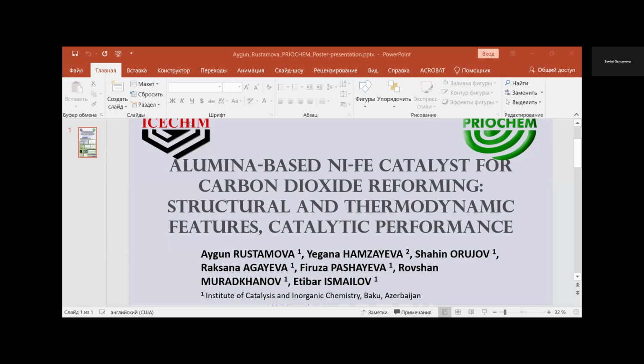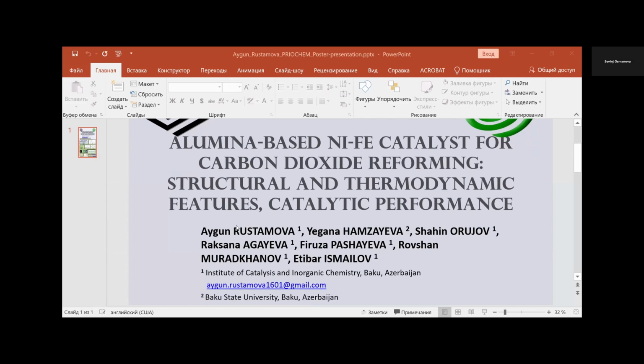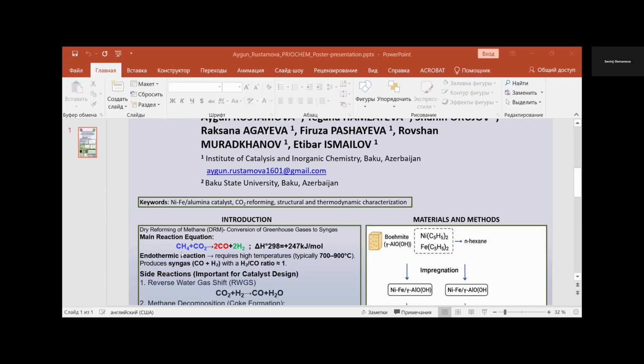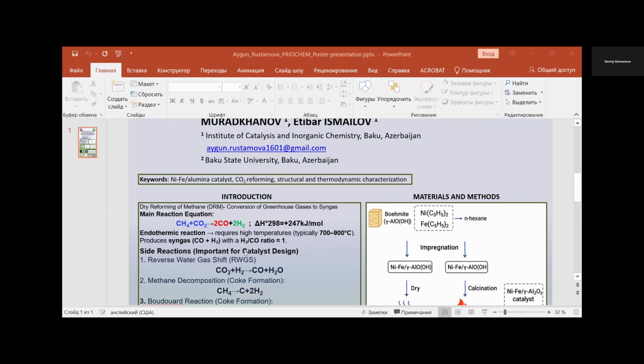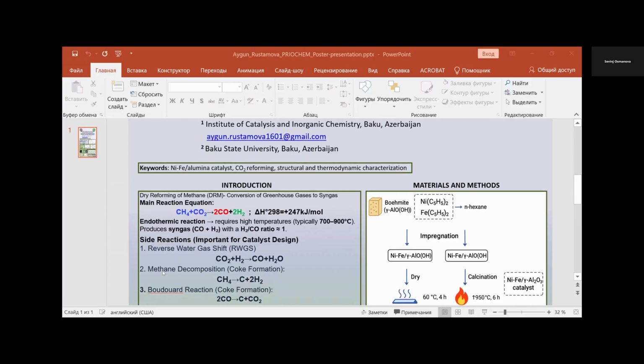My name is Shahin Orujov from the Institute of Catalysis and Inorganic Chemistry in Baku. I will present our poster on behalf of Yegane Hamzayeva. Our poster is about the aluminium-based nickel ferrum catalyst synthesis for carbon dioxide reforming. And what's actually the DRM, dry reforming of methane? The main reaction is shown here. You can see it's an endothermic reaction, and it's used for conversion of greenhouse gases to syngas. As well, there are some side reactions like reverse water gas shift and methane decomposition. And one more is the Boudouard reaction. The last two are related to coke formation, and it's not desirable in our case.